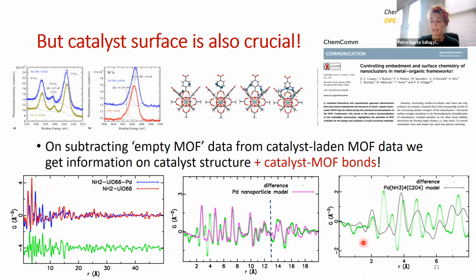However, there was a little trick here, because we tried to rationalize this data set in terms of, so we've got our pore here, we've got the palladium in there, and some of the surface palladium atoms could be bonded with the nitrogen, but most of them wouldn't, because in any pore there are only so many amino groups. However, the intensity of this palladium nitrogen peak is quite high, so we were unable to rationalize the intensity in terms of the embedding of these nanoclusters inside the pores.